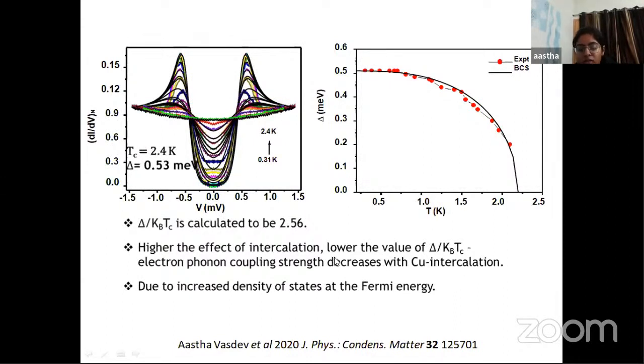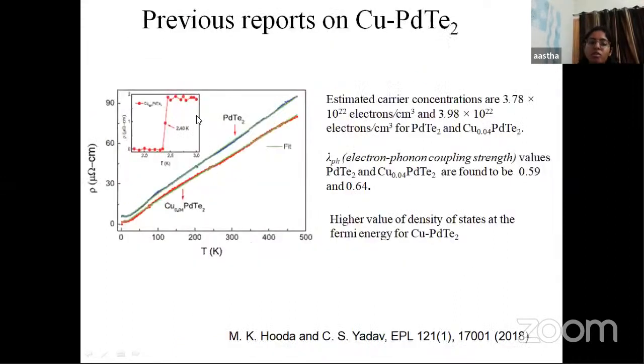Now, previous reports on bulk measurements on copper PdTe2 have reported that the enhanced transition temperature observed in copper PdTe2 is due to the enhanced electron-phonon coupling strength, as well as the higher value of density of states at the Fermi energy.